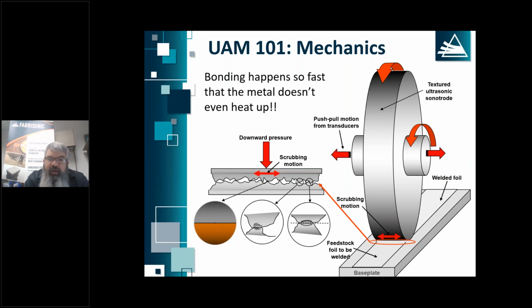The idea with an ultrasonic bond is to remove that oxide. So we're taking that welding horn, vibrating it left to right, and that's scrubbing the microscopic ridges and valleys on those metals. It turns out that most metal oxides are very, very brittle. So that scrubbing motion basically grinds away the oxide layer, kicks it out the side, and we have virgin metal on virgin metal. We apply a little bit of pressure, a little bit of force, pushing those asperities together, and we get a solid state bond. Now, certainly there's more to it than that, but that's the general idea: we're scrubbing to get rid of both the oxides and any contaminants. That exposes virgin metal on virgin metal, allowing us to get a solid state bond.